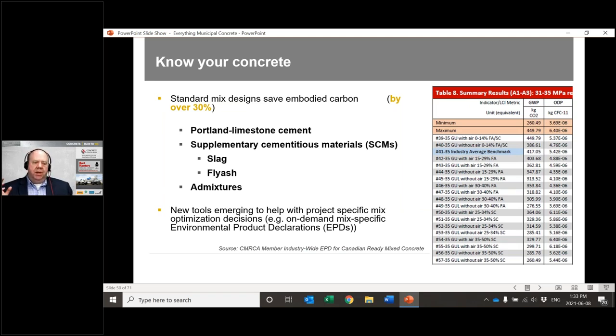When it comes to the concrete itself, then what are the real impacts? So I mentioned before, we need to start quantifying what the actual CO2 is in a cubic meter of concrete. So if we look at the CRMCA industry average EPD for concrete, this is an average for the whole country, and we look at concrete that's between 31 and 35 MPa in compressive strength, we see that at its lowest end, it's 260 kgs of CO2 per cubic meter. And at the high end, it's 450 basically. So what's the difference? Well, the high end is 100% GU cement and nothing else. So if you're just using GU cement, then you're gonna have the highest possible carbon footprint.